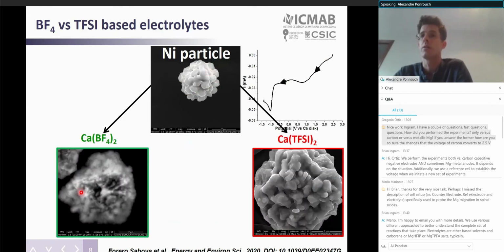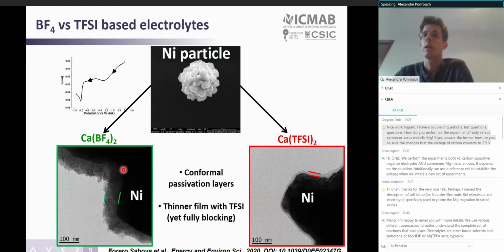In these two electrolytes, from scanning electron microscopy, you can see some difference in morphology for the passivation layer being formed. From TEM microscopy, the passivation layer formed in the calcium TFSI based electrolyte was significantly thinner and smoother than the one formed in calcium BF4, although this very thin passivation layer was enough to fully block the electrochemistry.